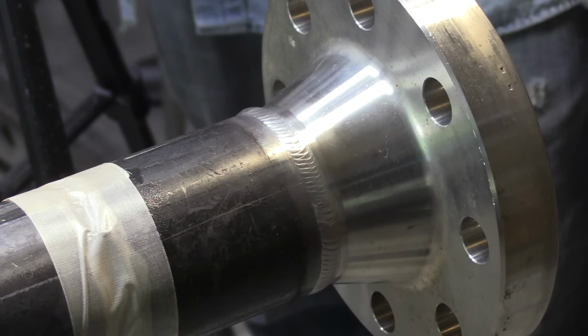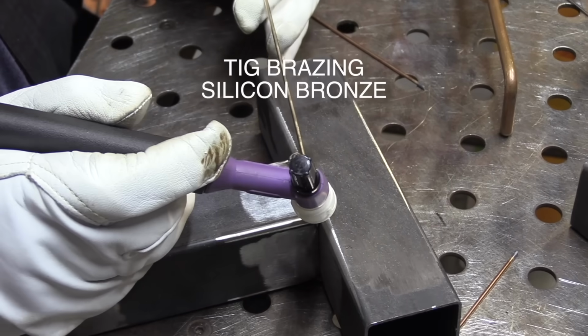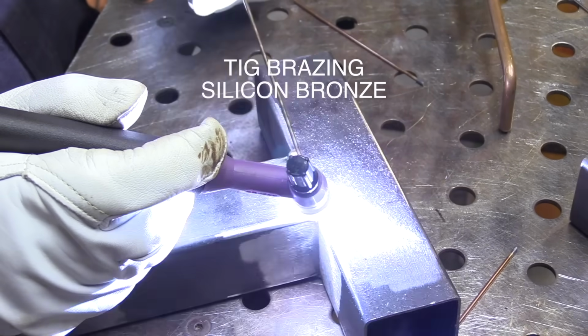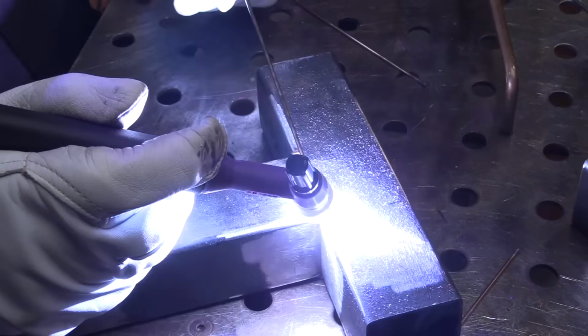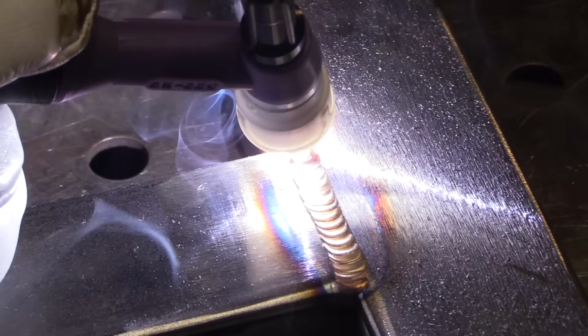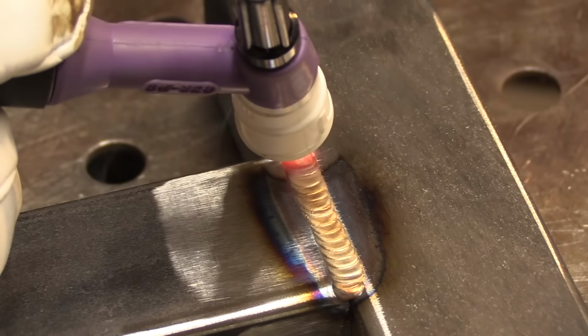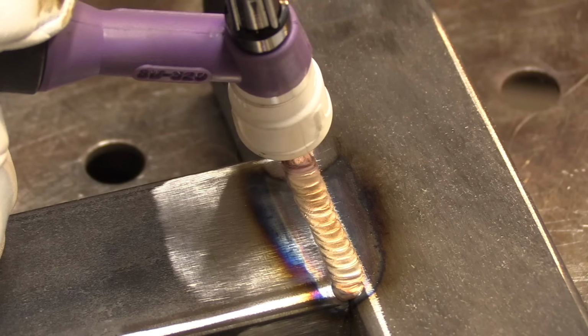TIG brazing is using silicon bronze or some other aluminum bronze or something like that, where you're not really melting the base metal but you're just melting the filler metal. I find that about 2 pulses a second with about 20 or 30% background does a great job. For TIG brazing, it really helps to have an oversized cup.